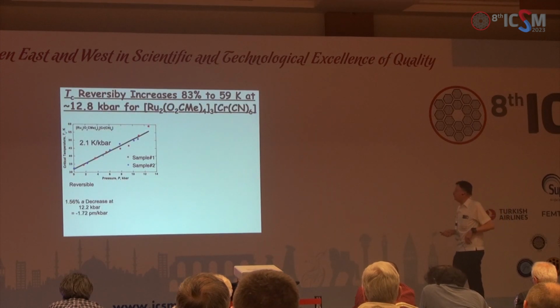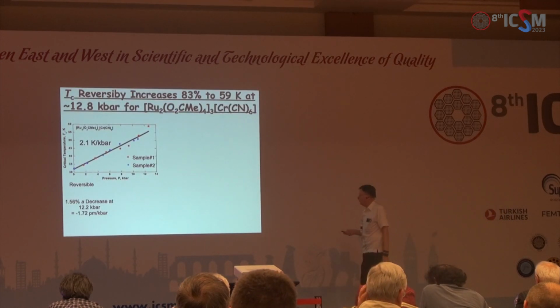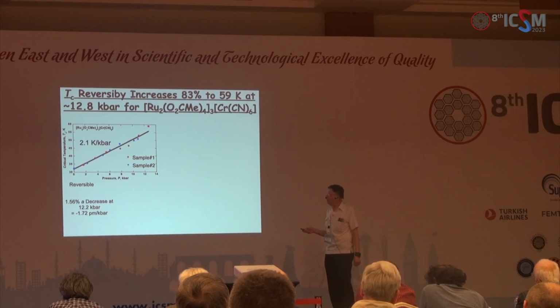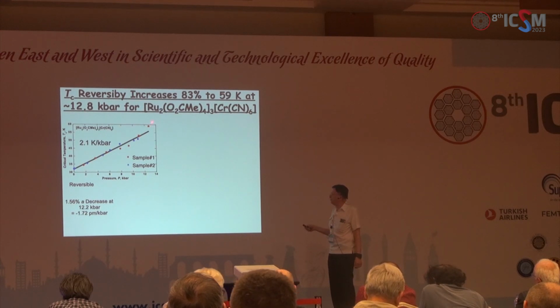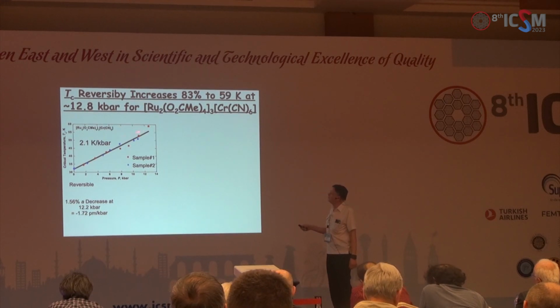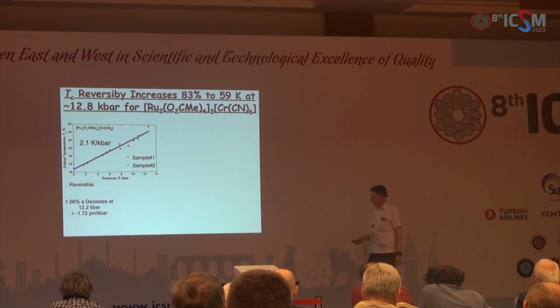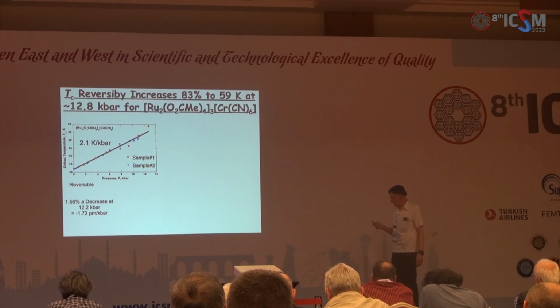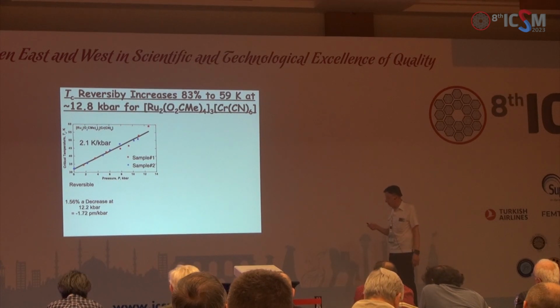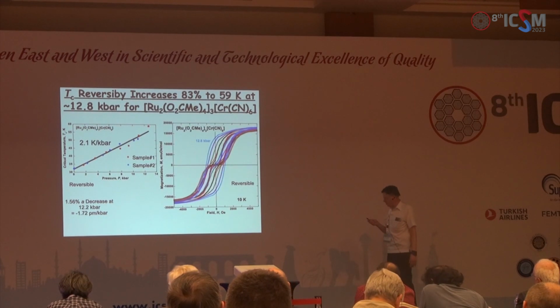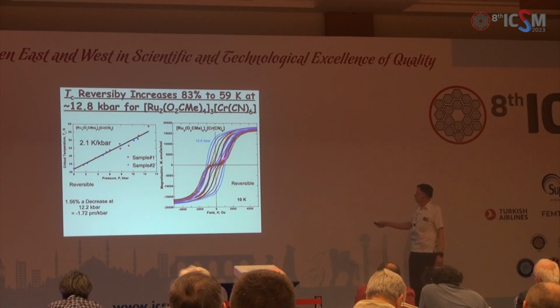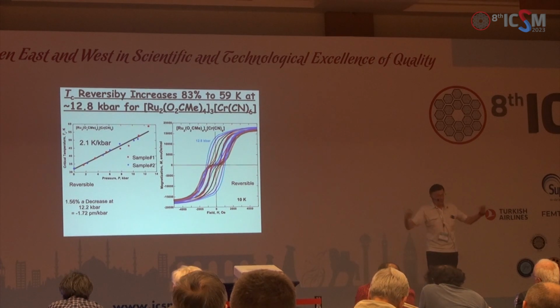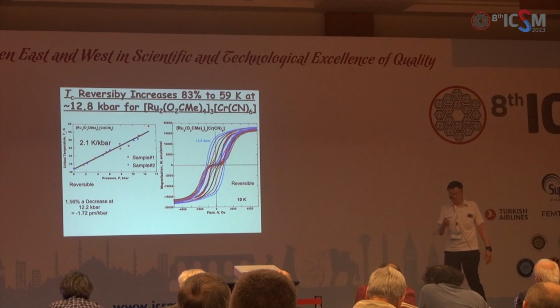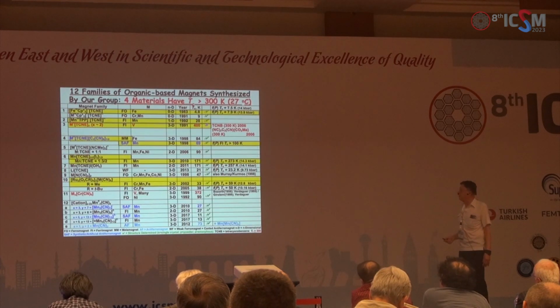If you put pressure on it, Tc goes from 33 Kelvin and increases at a rate of 2.1 Kelvin per kilobar of applied pressure, linearly and reversibly. So it goes up to about 60 Kelvin under pressure, at least up to the pressure limit we used. But more interesting, the hysteresis loop, shown in red with the constricted nature, becomes normal-shaped after you apply pressure, and if we remove the pressure, it goes back to the funny shape. So it's a very interesting compound.